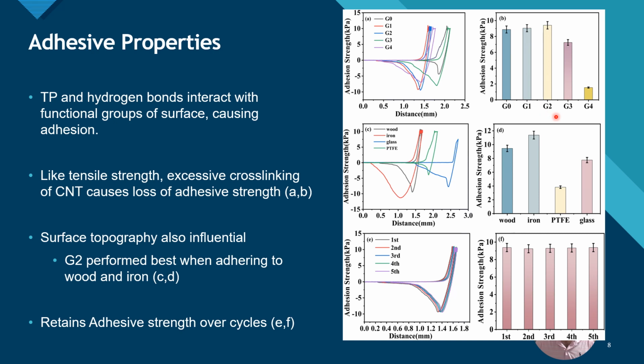We then took our G2 sample and compared it across a variety of different substrate surfaces. We found that wood and iron resulted in the largest adhesive strength, followed by glass, then PTFE. This shows us that topology of the substrate also plays a key factor in the adhesive force. Lastly, we were concerned about the adhesive strength over cycles, specifically as it regards to shelf life and reusability of these sensors. So the sensor was taken and debonded 5 subsequent times and rebonded, each time measuring the adhesive force. We found a retention of 99.5% of the adhesive force over 5 cycles.